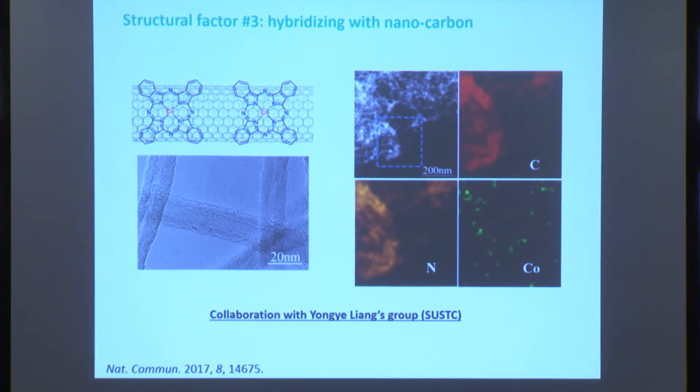Okay. So this is another case where the metal ion and the ligand work together to do CO2 reduction. And I was mentioning that in those cases where we just load a lot of molecules onto the electrode surface to form a film, as a catalytic electrode, it is not a great way of getting an efficient electrocatalyst, simply because those organic compounds are not really conducting. And once you pile a lot of them onto the electrode surface, the catalytic sites are not well exposed. So these are not good factors for an efficient electrocatalyst. In order to make a good electrocatalyst, you want those active sites to be well dispersed. You want them to be sitting on something that is really conductive.